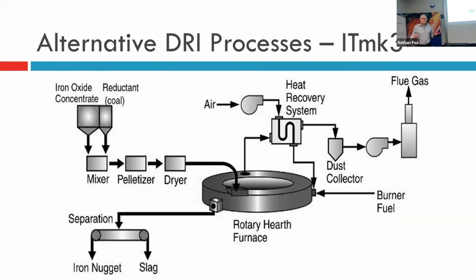You pelletize it and dry it, and then put it into a rotary hearth furnace. That furnace is heated up to around 1,000 degrees. There's a dust recovery system associated with it. But what happens to the pellets of iron oxide and coal is they react together and get into a semi-molten state, so they come out as a globule of iron, which I think I've got a picture of in the next slide. That's the sort of product you get out from it.